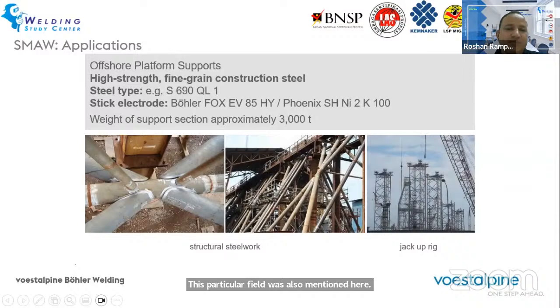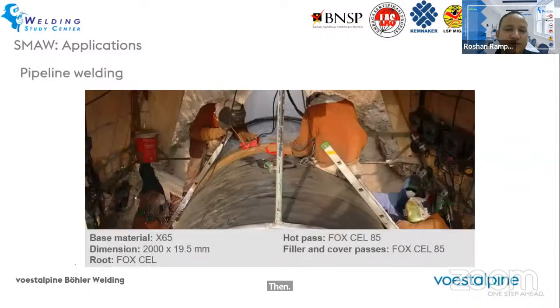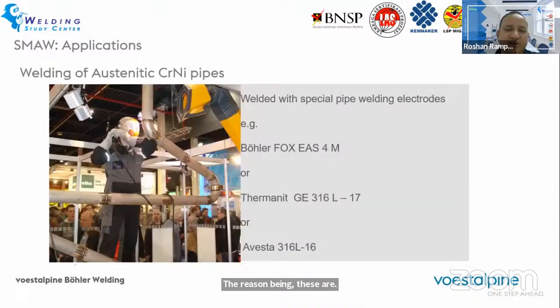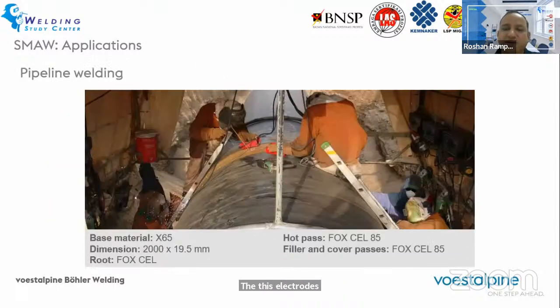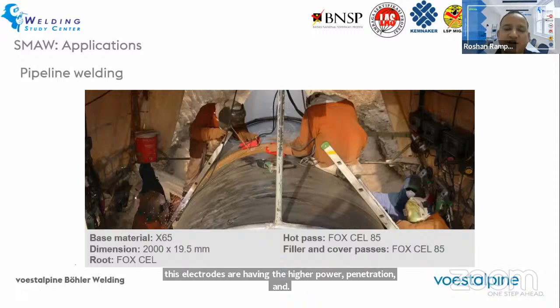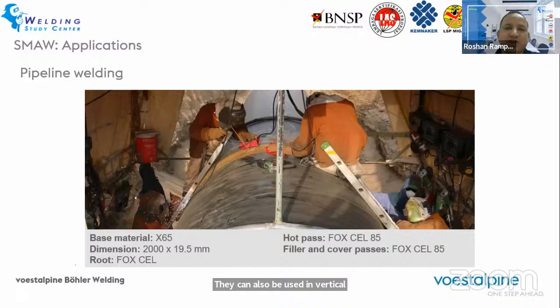Then pipeline welding, the most common type of electrode are cellulosic electrodes used for cross-country pipeline welding. The reason being the cellulosic electrodes have higher arc penetration and they can also be used in vertical downward position without any problem with the control of the weld pool. So cellulosic electrodes are the most common type of electrode used for vertical down position, especially for cross-country pipeline application.